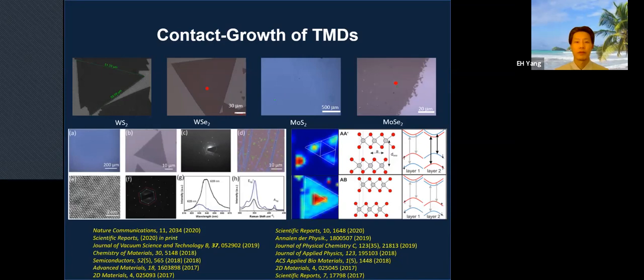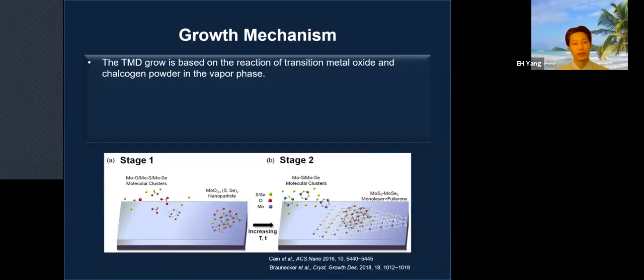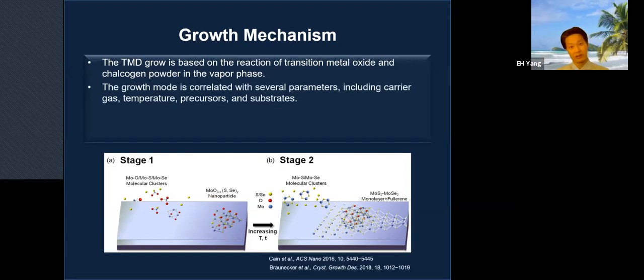So what we do here is to grow these, and we in situ dope iron here. The growth mechanism is based on the reaction of transition metal oxide and chalcogen powder in the vapor phase. Of course, the growth mode is correlated with several parameters, including gas, temperature, precursor, and substrate. So this is easier said than done. It's not that simple, one line of thing. You have to put thousands of hours into developing this process.